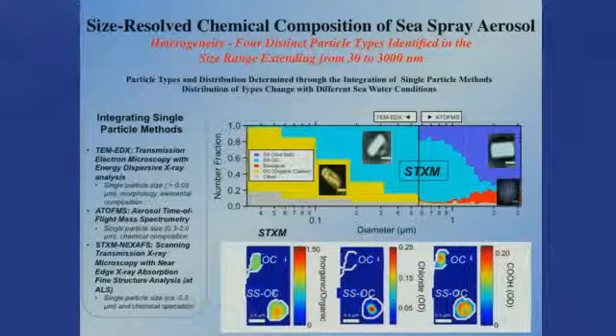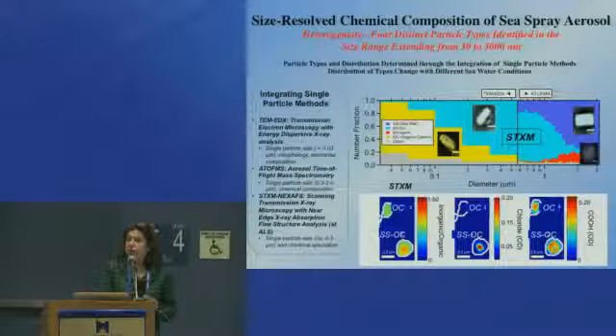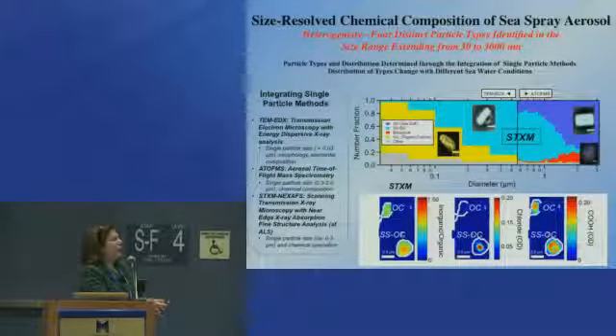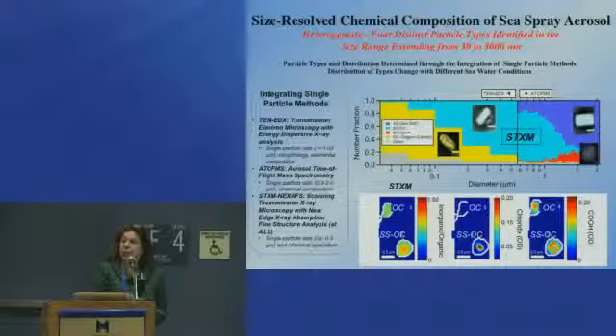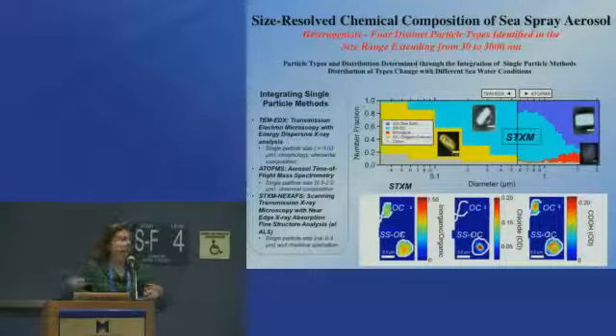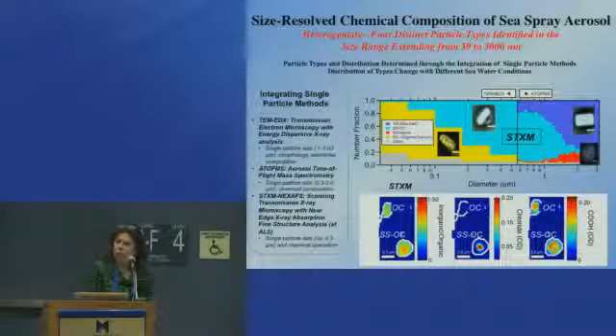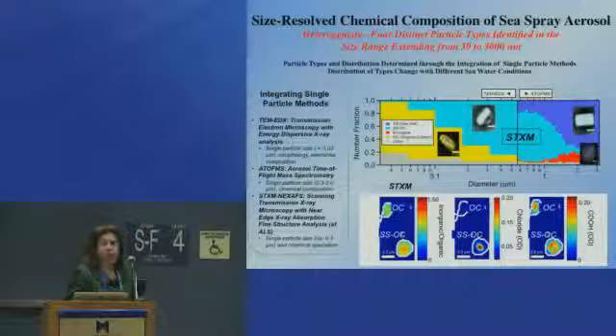What we found is that for the larger particles, some of these look really like sodium chloride, just as people had expected. But as you get to smaller size, and even at larger size, there are other things. Here in red are biological particles. Here is the legend over here. There's another group of particles that we call sea salt with organic carbon, so they have some coatings around them. And then we have some particles which do not have a sodium chloride core at all. Here's just one image, and we've been collecting more, and Kim showed you the cryo-TEM of some of these that occur at smaller size. So we really had to work hard to integrate these methods. A little kludgy, if you will, but I think we were able to get a start of a story of how the chemistry and composition of these particles change as a function of size. So a lot is coming out of the ocean, and it's very much more complex than just a simple sodium chloride description.